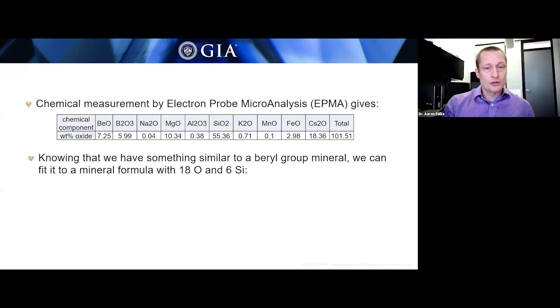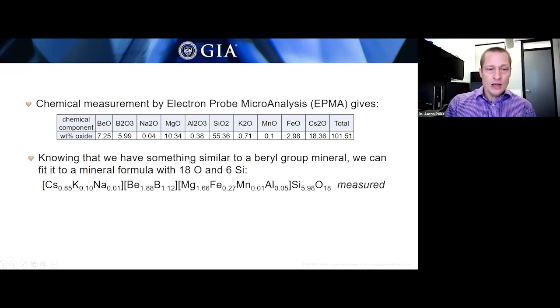So we know beryl group minerals have 18 oxygens and 6 silicon atoms in their chemical formula. So if we take the data above and reduce it to the chemical formula, as measured, we get something that looks like this. It's pretty messy because there's a lot of different chemical elements going on in there. But we see the 6 silicons, the 18 oxygens. We have a lot of magnesium in this particular site where you expect to see aluminum. In the site where you have only beryllium in beryl, we have some boron in there as well. And then we have this additional crystallographic site where there's a lot of cesium, potassium, and sodium, which is not in the ideal beryl formula.